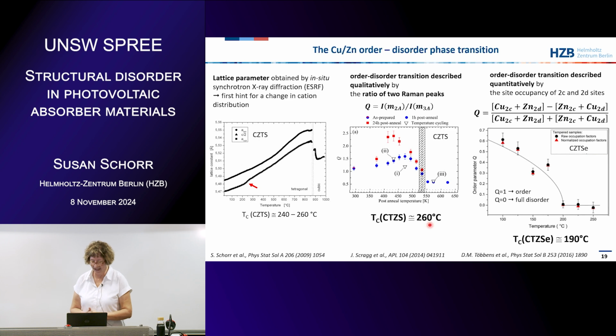Based on that, later again, you see from the years of the publications, we did a study on copper zinc tin selenide where we used anomalous synchrotron X-ray diffraction, and with anomalous diffraction you can then distinguish between copper and zinc, and so we had already defined the order parameter from that formula. This is the order parameter here over the temperature, and you see very nicely these are annealed at a certain temperature and quenched samples. The order parameter is 0, that means you have full disorder, and then it increases, so the disorder gets less and less. But you see that we have not reached one. It will take almost forever to reach full order.